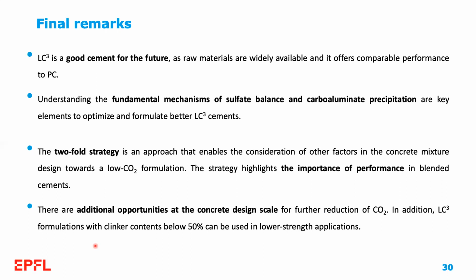The strategy highlights the importance of performance in blended cements. There are additional opportunities at the concrete design scale. I mentioned three of them: use of admixtures, aggregate design, and the use of high performance SCMs. In addition, we can use formulations of LC3 with lower clinker contents below 50% in lower strength applications.